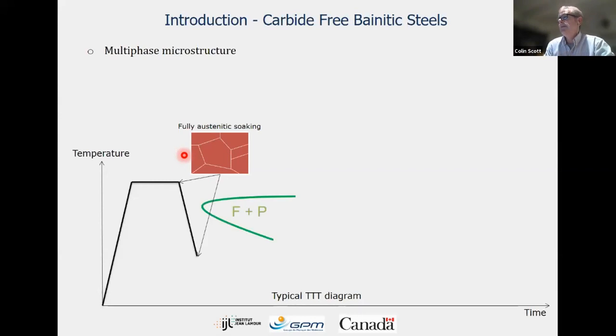Then we go fast cooling. So we can cool at 50 degrees C per second. So we use special hollow samples in a dilatometer that's installed in the X-ray beam line. So we could control at 50 degrees C per second. That means no ferrite is forming, no pearlite.